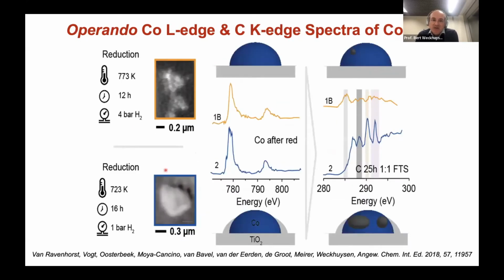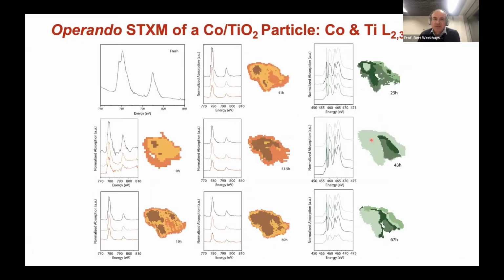Now, depending on this different treatment, and hence different spectra, more cobalt metal, more cobalt titania, you can see that you have also different spectra in the carbon K-edge. That means you can measure what is happening at the surface of this cobalt nanoparticle.